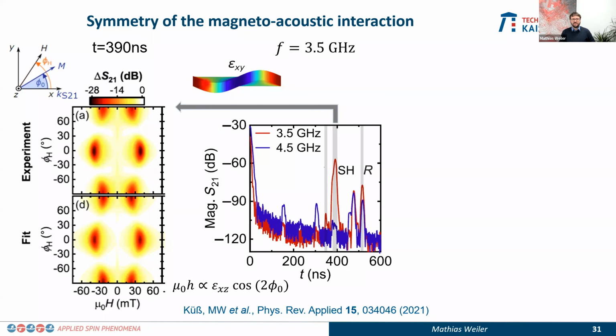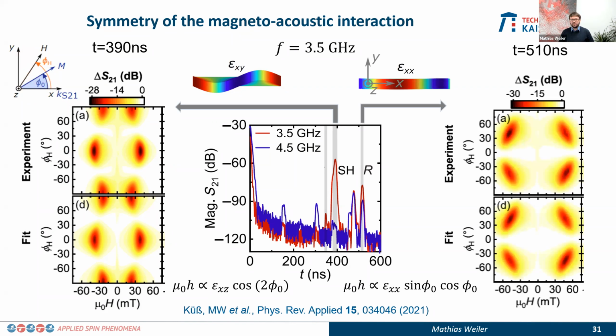And then we can look at the symmetry of this magneto-elastic interaction. So what should be the ideal orientation of the external magnetic field to get an interaction? You can see here, if you use the shear horizontal wave, that the ideal orientation of the external magnetic field is basically along x, along the propagation direction of the sound wave, and with that the spin wave exactly along y, meaning orthogonal. Okay? And that's different from what we observe in the very same sample, in the very same measurement even, with the Rayleigh wave. Because that tells us the ideal orientation of the external magnetic field should be about 45 degrees, or the magnetization has to be at 45 degrees to the propagation direction.